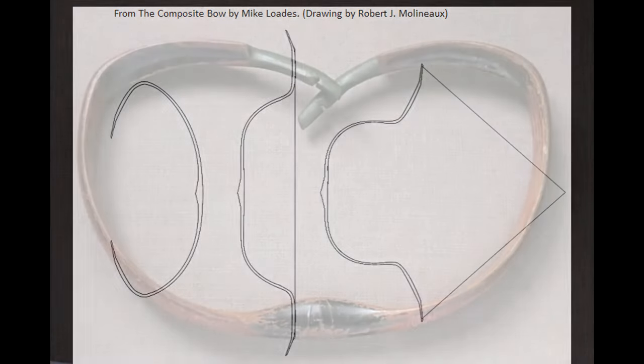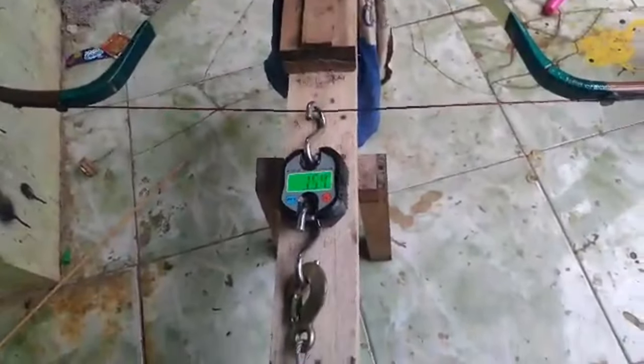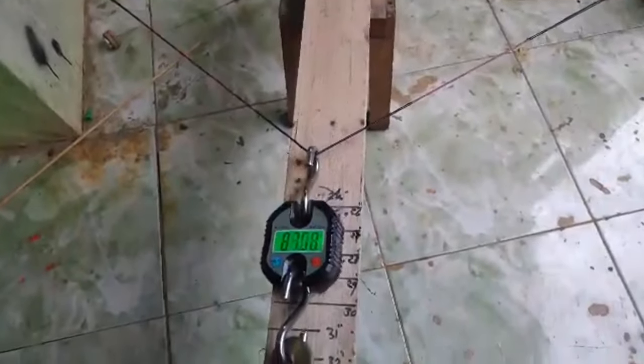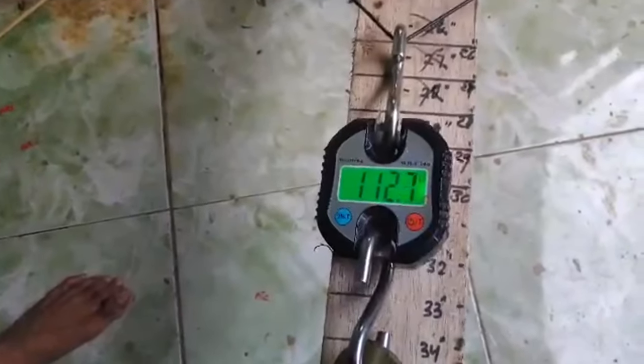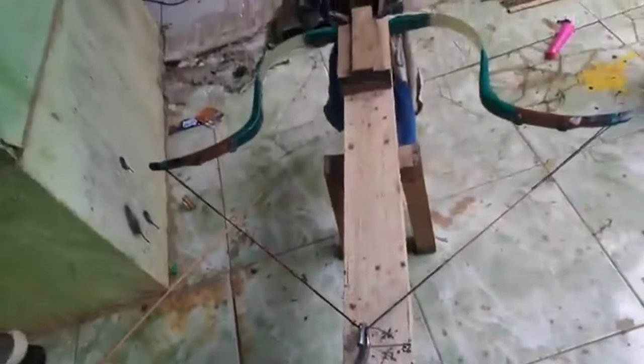This shows the superiority of organic horn-and-sinew composite materials in elasticity. But my bowyer, Toto Alharas, nonetheless attempted it with fiberglass. The end result is a bow that can only be pulled to 26 inches according to the bowyer. I've seen successful crossbows made of fiberglass at 50 pounds pulled to 28 inches, but nothing of this draw weight. I think this is the first one above 100 pounds that's made of fiberglass.